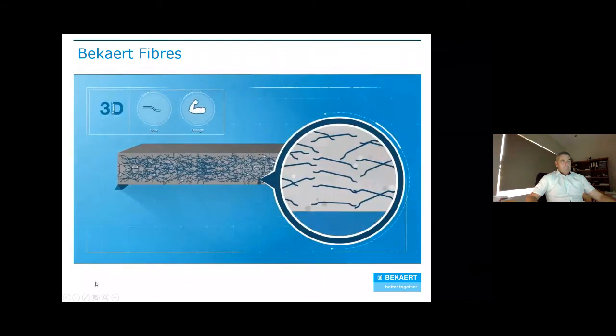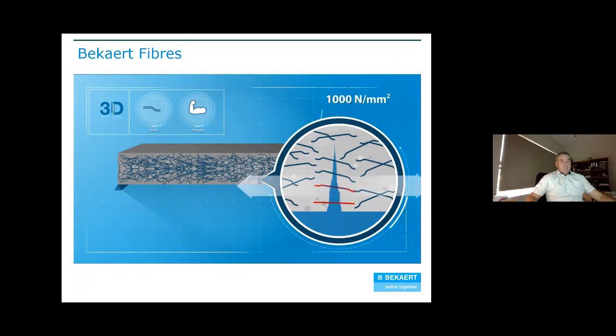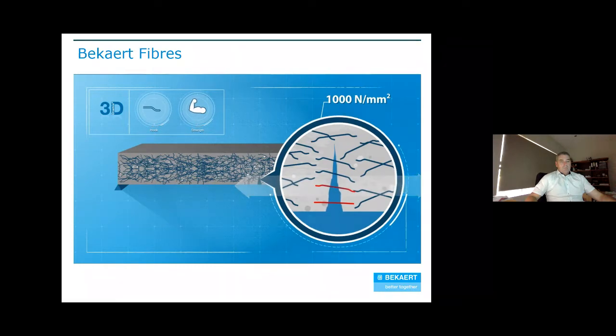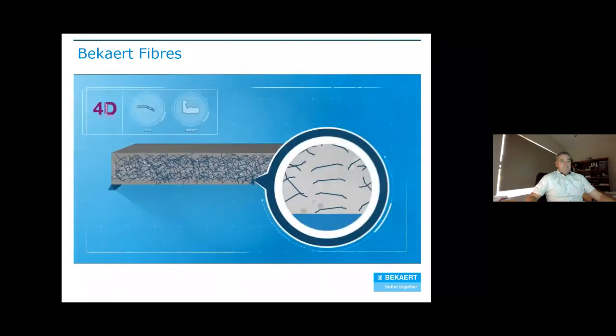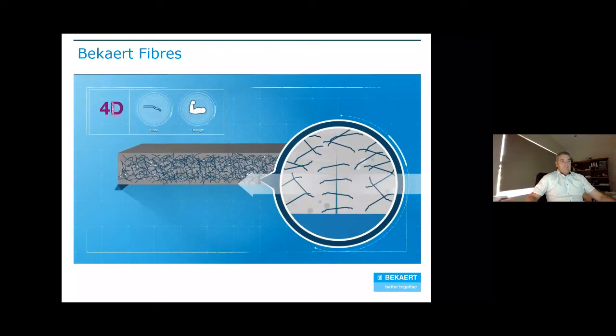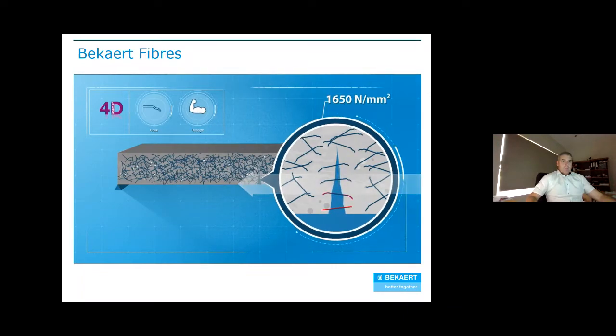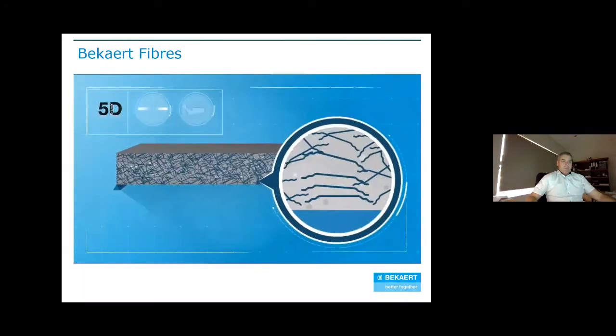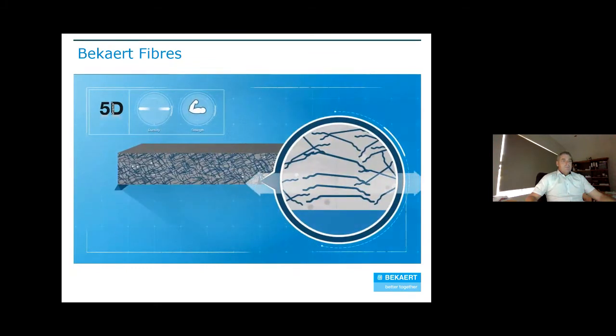When a small crack occurs, the 3D hooks firmly anchor inside the concrete matrix. As the stress increases, the hook slowly deforms. As soon as the fiber loses its bond with the concrete, the pullout takes full effect. Dramix 4D provides the same process, but with even better anchorage and a significantly higher tensile strength of 1,650 Newton per square millimeter or more. Dramix 5D behaves differently altogether.